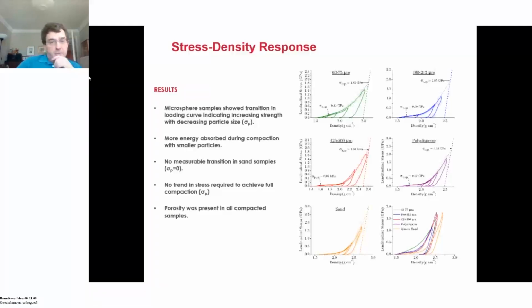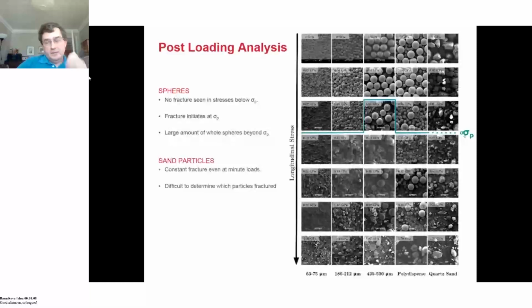We recovered the samples and basically discovered, and here you can see a line amongst these pictures, this sigma p. Basically, this is the stress at which we saw fracture in the spheres, and we're always getting fracture in sand here, so that's why I've got this dotted line. But you can see very clearly there is a stress at which the spheres fracture quite strongly. It's at a certain level.